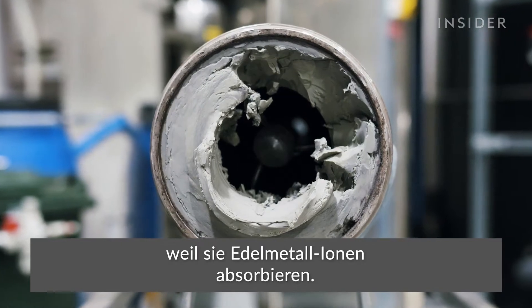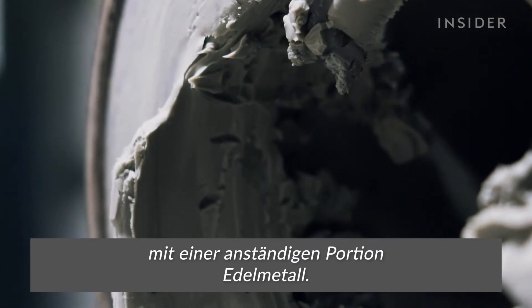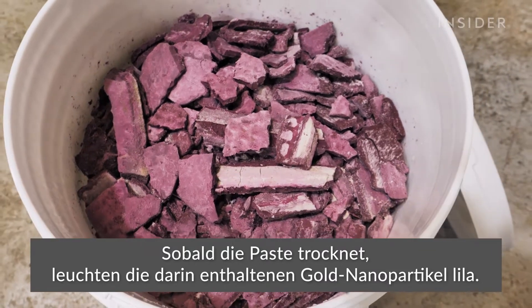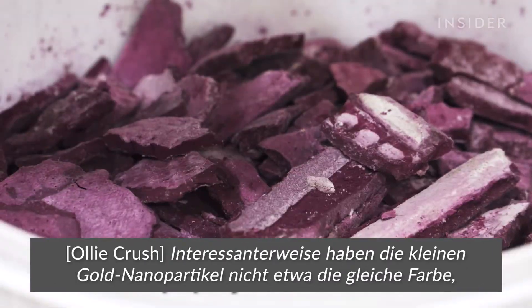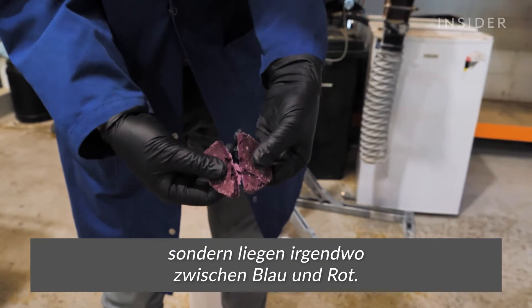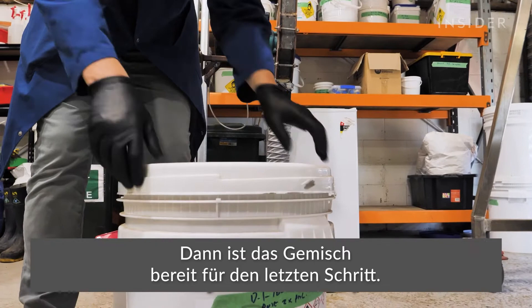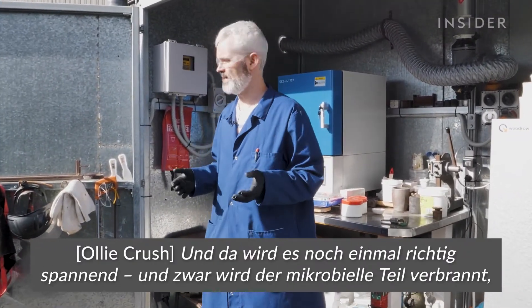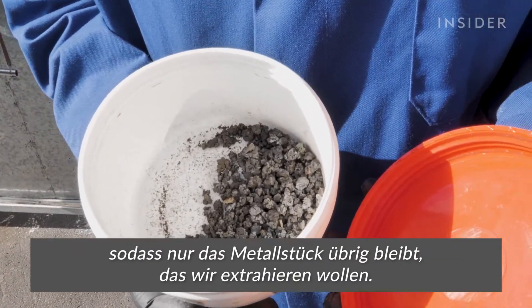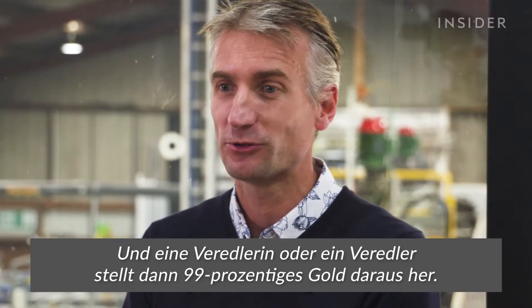Over several hours, the microbes gain weight as they absorb precious metal ions, producing a concentrated microbial paste that contains a good portion of precious metal. When the paste dries out, the gold nanoparticles in it start to appear purple — gold has the funny property that when it exists as small nanoparticles it takes on hues of blues to reds. The mixture is then ready for the last step, where the microbial part is burned off, leaving the metals they've captured behind.